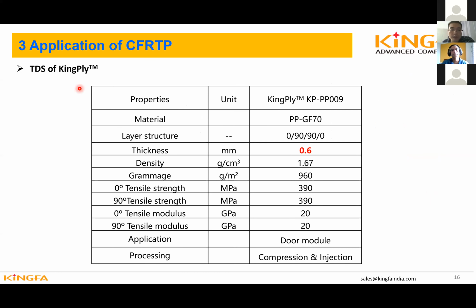Then we come to the KingPly. So for this material, we have 4 layers. The thickness is only 0.6, and because we have 0 degree, 90 degree, 90 degree, and 0 degree, the 0 degree and the 90 degree property is the same. There's no big difference. That means if we use it in our final product, the property is much more uniform.